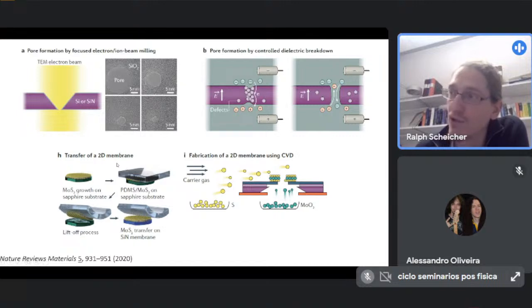And then I will talk a lot about, when I'm coming to the part about our own research in modeling this kind of nanopores, I will talk about two-dimensional materials. And so with two-dimensional materials, there are different ways to do it. You can either grow these 2D materials on some kind of a substrate, like shown here on the example of molybdenum disulfide, and then transfer it, in some process that is indicated here, onto a silicon nitride membrane, and then make the nanopore in this 2D material on the membrane.